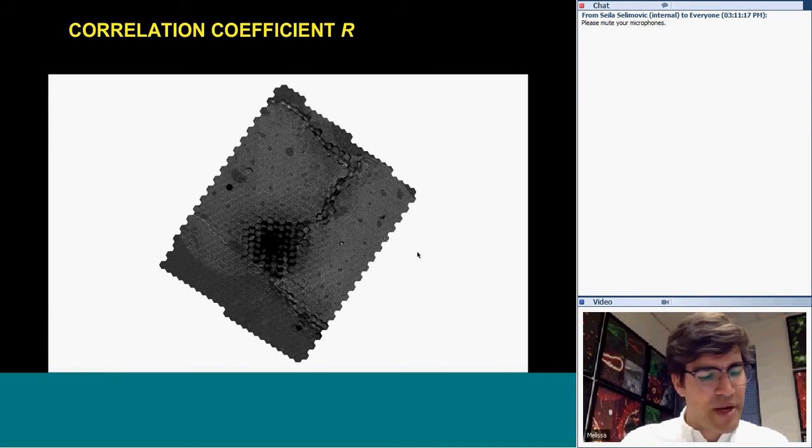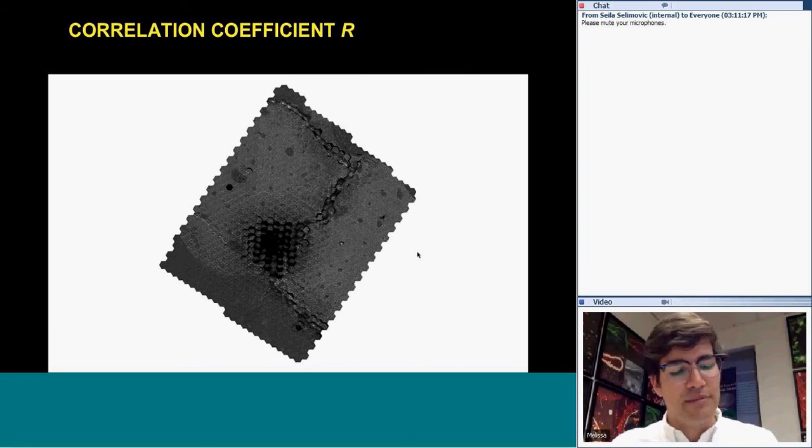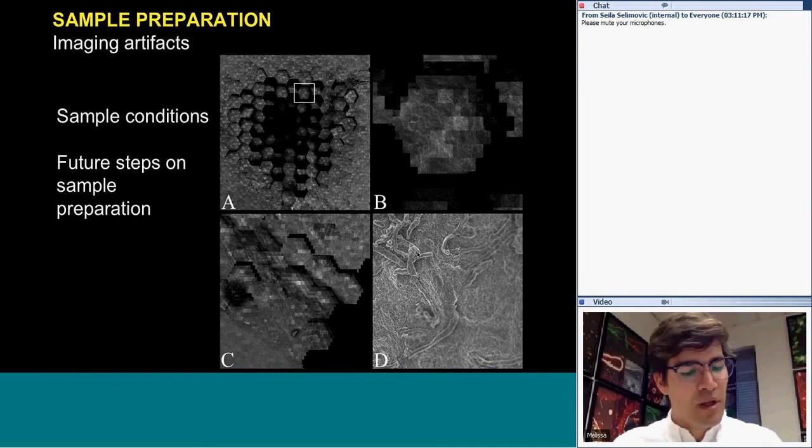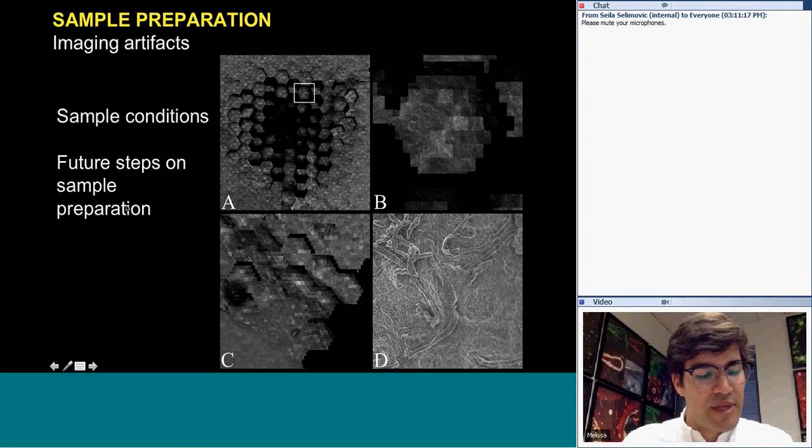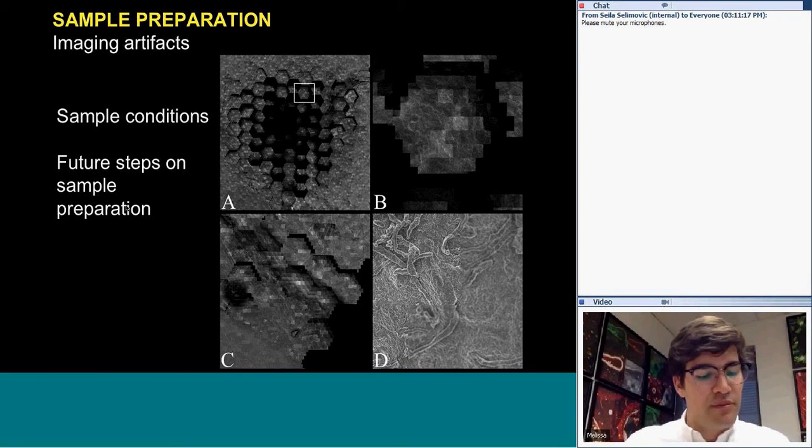Just as a reminder, this is just an overview of a first successful map of the human hip. It worked as a first feasibility study to develop, validate, and improve the methodology. So why did we obtain those low quality images? In some cases, this had to do with the sample preparation process. Basically, some of the sample regions had topographic depressions and cracks, and these were created by residual stresses in the microscopic samples, which were released during the sample preparation process.